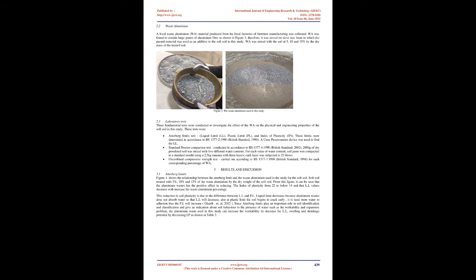3 Results and discussion. 3.1 Atterberg limits. Figure 4 shows the relationship between the Atterberg limits and the waste aluminium used in the study for the soft soil. Soft soil treated with 5%, 10%, and 15% of the waste aluminium by the dry weight of the soft soil. From this figure, it can be seen that the aluminium waste has a positive effect in reducing the plasticity index from 22 to below 14, and that LL values decrease with increasing waste aluminium percentage.